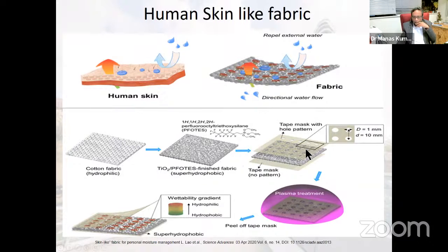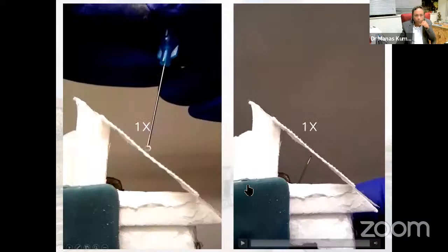And the bottom mask does not have any holes. After doing this, we put this whole thing in the plasma treatment so that the fabric is treated to become hydrophilic only in these mask portions. So doing this, we achieve a gradient from hydrophobic to hydrophilic. The outer portion becomes more hydrophilic, whereas this one becomes a little bit hydrophobic, increasing in hydrophilicity towards the other side. So this way a benefit was observed.